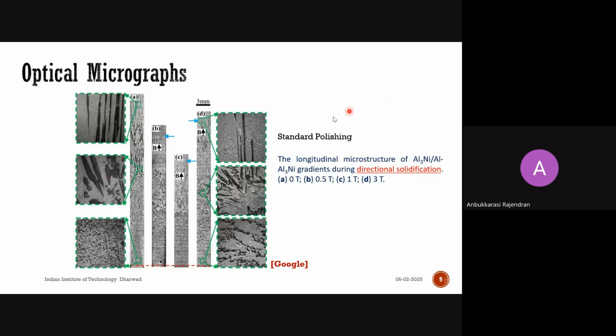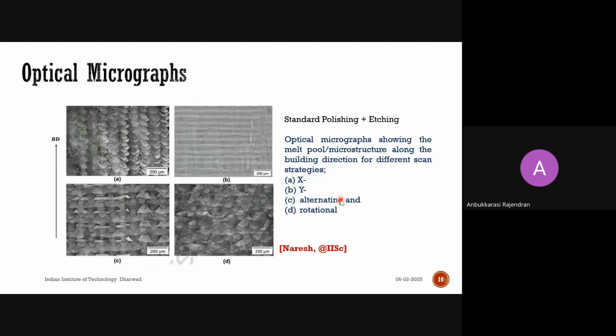This is only direct polishing. After polishing, these needles can be seen. So here we have not used etching for revealing any internal structure. Okay, this is one of the structures from an additive manufacturing deposited layer. But in this case, the etching procedure is required.